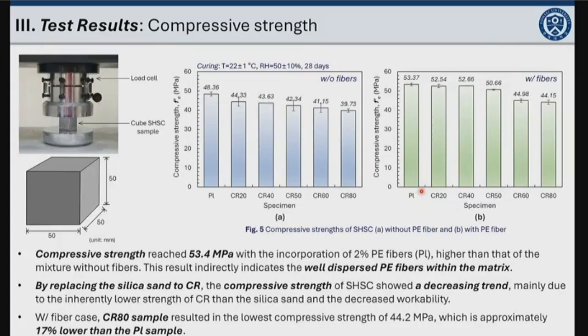By replacing the silica sand with the crumb rubber, the compressive strength showed a decreasing trend, caused by the inherently lower strength of the crumb rubber than the silica sand. In the case of 80% replacement, the lowest compressive strength of 44.2 megapascal was obtained, which is approximately 17% lower than the plain sample.